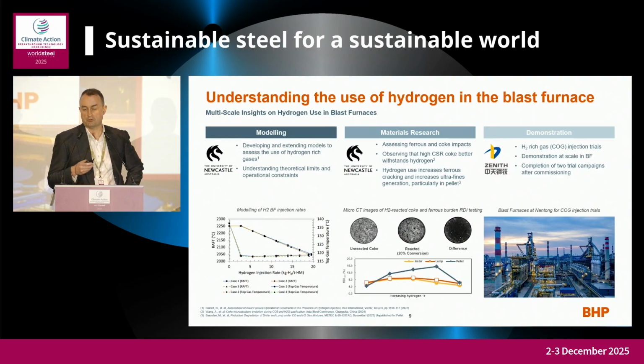And some early learnings coming through is really that high quality coke can play a key role in resilience against hydrogen attack. And then there's some trends in the ferrous burden RDI that we're seeing around the impact of hydrogen on pellet degradation versus sinter and lump, but we've got to understand that a bit further. Ultimately, we see the raw materials will play a role in decarbonising the blast furnace, and high quality coke is going to be very important as you're trying to reduce fuel rates significantly. So understanding the performance of that coke and the coals that go into it and how you generate that quality is important.